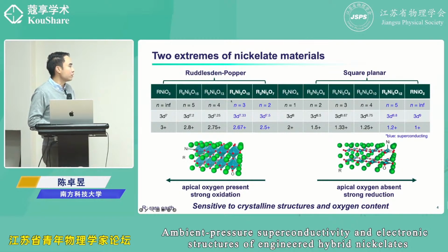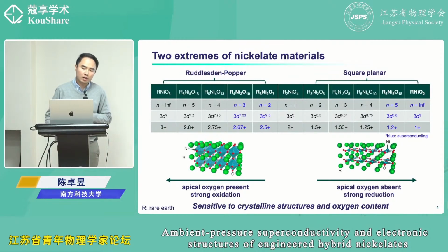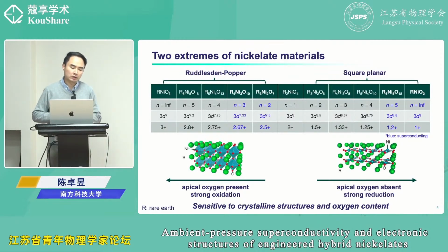This ratio difference is quite small. And so if you're not controlling the growth or the synthesis parameter so accurately, you will have a lot of intergrowth and different phases within the same crystal you grow. So it's also very difficult to control the crystalline structure.